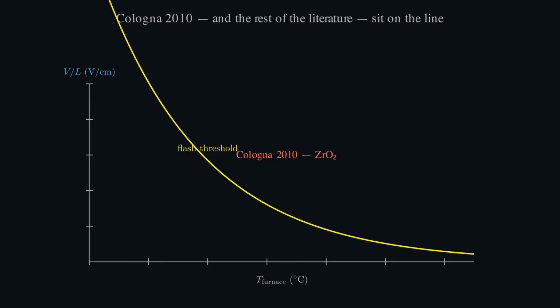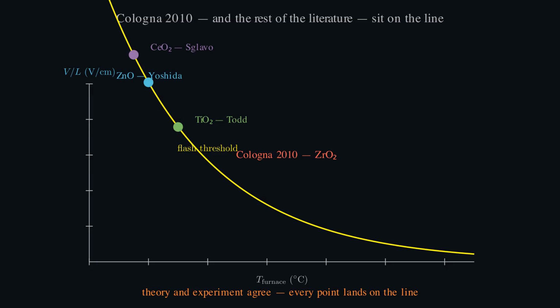Drop in the rest of the literature. Todd's titania, Sglavo's ceria, Yoshida's zinc oxide. They sit on the boundary too. The theory and the experiments agree. If anyone ever measures the true core temperature of a flashing sample in real time, the mechanism debate ends. Until then, the equation is what we have. It is enough to design experiments. It is not enough to explain them.